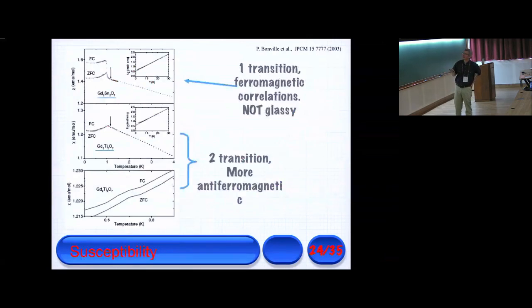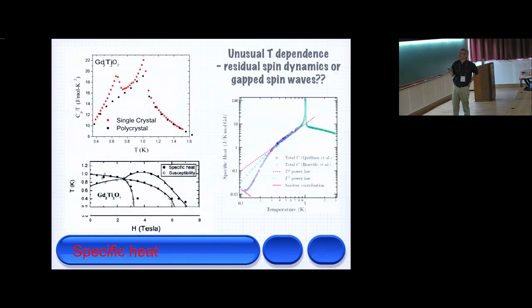So here is some more, so this is the susceptibility. The stannate, there's one transition, but then when we do field cooled, zero field cooled, there's a splitting, so that's not normal for an ordered antiferromagnet, so that already starts to bring in questions. In the titanate, there's splitting, and there's also a kink here, suggesting a second transition, which we had previously seen